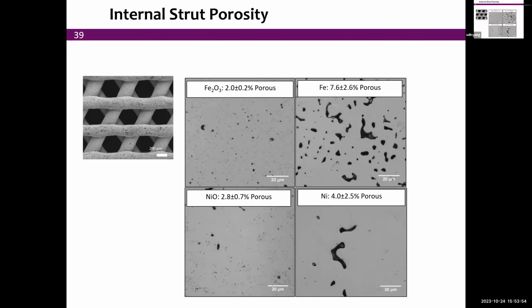Okay, so as a result, the porosity within the struts, those are cross sections, we see that for iron oxide, because it's very fine, it really sinters very quickly, and so is the case for nickel oxide. Whereas for iron and nickel, we end up with residual porosity that may be in the 4 to 8% region.